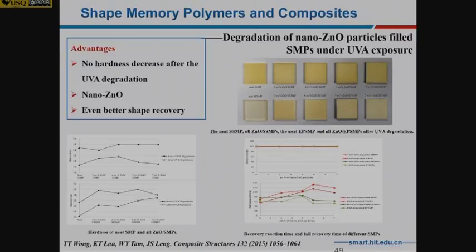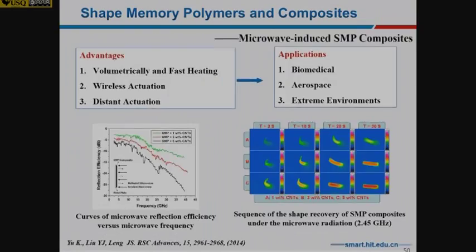So we also have collaboration with Leng, and we're using nano zinc oxide nanoparticles to improve UV resistance, because zinc oxide has good properties to resist UV light. With this, we can find that with the nanoparticles there is no degradation after UV exposure for the composite. That means you can try a lot of composites to give you different properties for the shape memory composite. So we also try microwave.